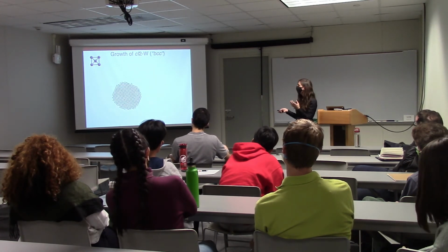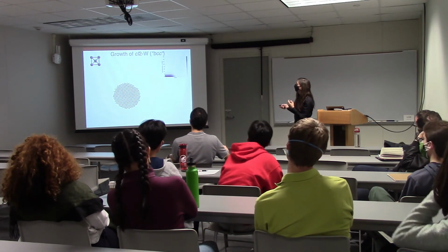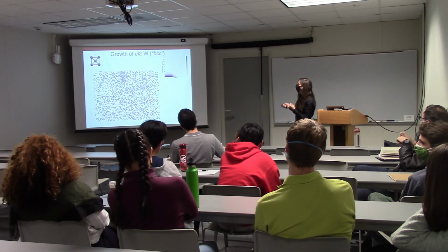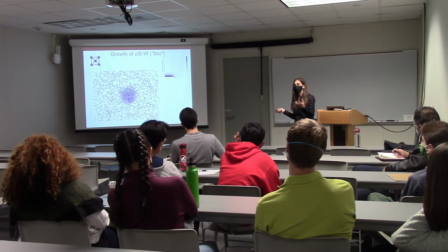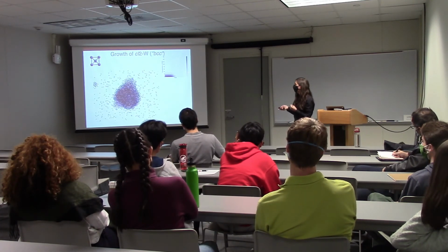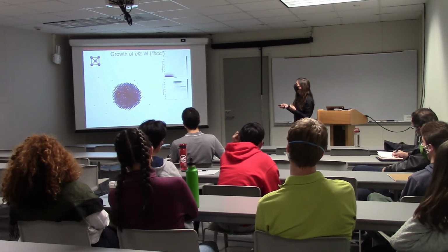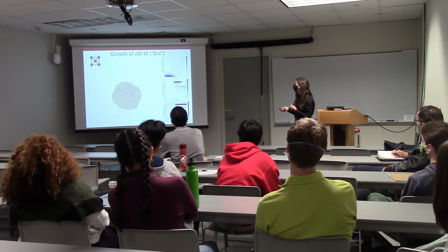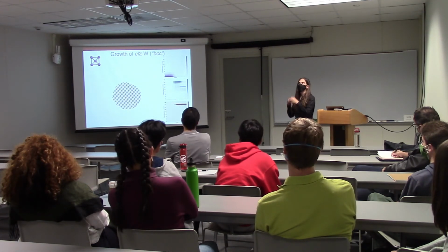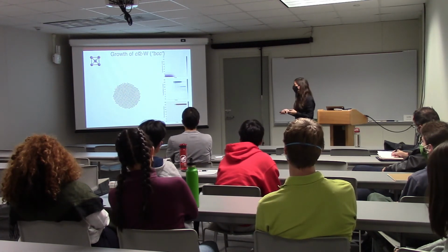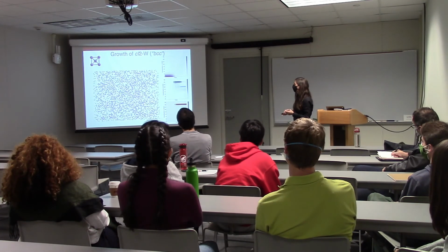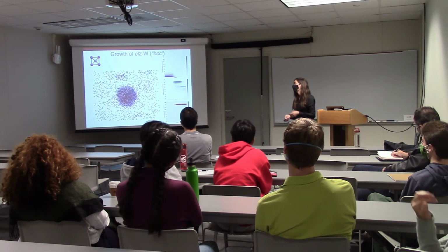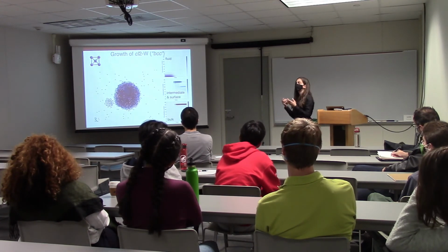So 3 different environments. If you look at these clusters and the coordination numbers over time and how many of those particles you have, you can see that the gas particles are low coordinated, that makes sense, and they disappear over time. This is where condensation happens, and initially you have just your fluid droplet, and at the very end you have your crystal condensed. So 14 nearest neighbors, that's your BCC structure. And you have some that persist at the very end, that's the surface particles. So this is relatively straightforward.